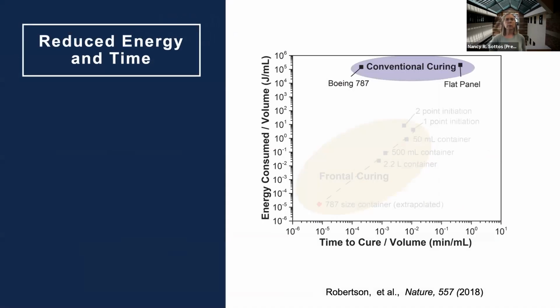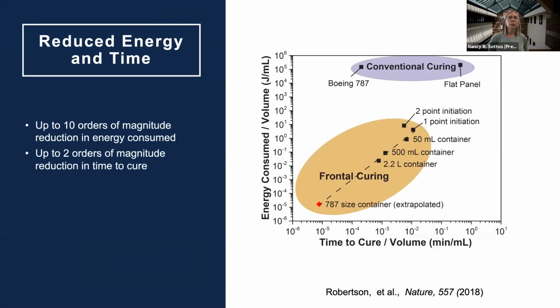So if I go back to the Ashby plot I started with, and talking about reduced energy and time was our objective, with this frontal curing, we really achieved a number of different things. We were able to, with our 1 and 2 point initiations, really reduce the amount of energy per unit volume by several orders of magnitude, and significantly reduce the cure time for a panel. If we also did this little plot where we extrapolated to just different containers of resin, looking at the energy required. And again, this gives you this notion that it doesn't scale with volume in the same way that an autoclave cure does. And we extrapolated this all the way back.